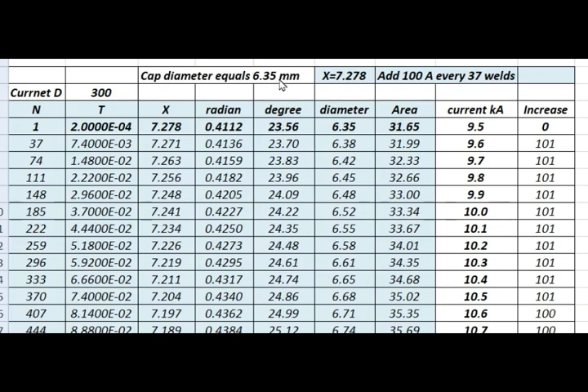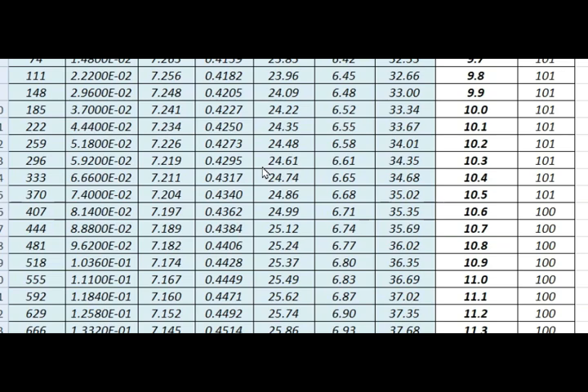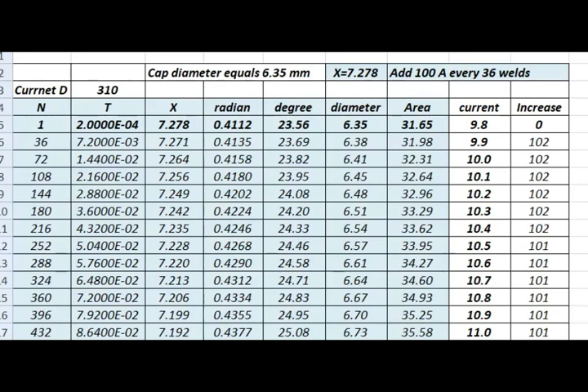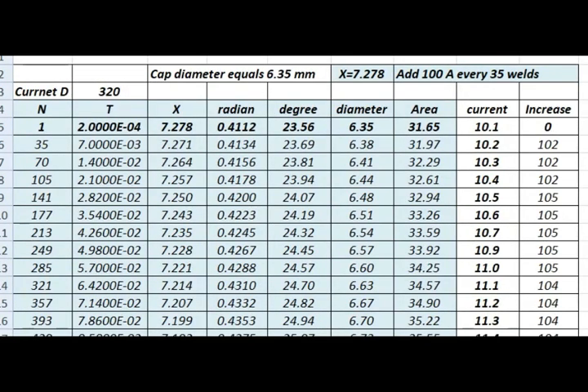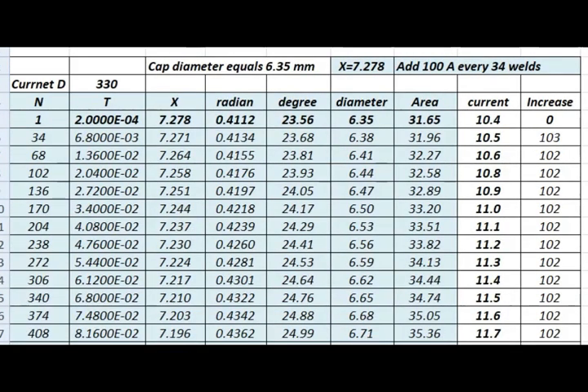Most people use a 6.35 mm or quarter-inch B cap to weld. The x1 has to be recalculated and the start current has to change also. This new spreadsheet looks like this. Welding at 310 amperes per square millimeter, add 100 amperes every 36 welds. Welding at 320 amperes per square millimeter, add 100 amperes every 35 welds. Welding at 330 amperes per square millimeter, add 100 amperes every 34 welds.